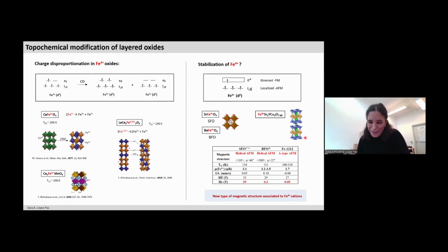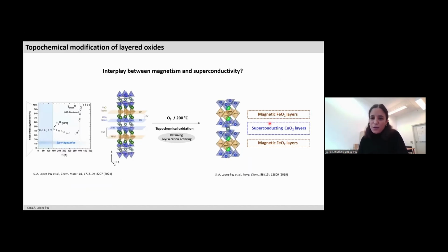So beyond the interest in discovering new magnetic compounds, we need to remember that this compound was actually superconducting. So by using this low temperature oxidation approach, we were able to design a material in which we have magnetic monolayers of iron 4+ cations alternated with our superconducting blocks. So this provides an ideal framework to actually study the interplay between magnetism and superconductivity.